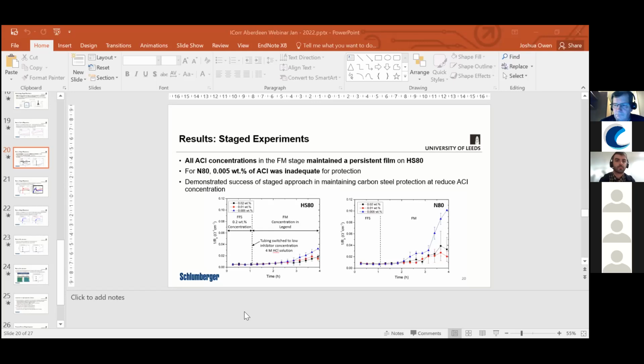It's very high. It's from 700 to 1,000 millimeters per year. It's not surprised us. So it also depends on acid concentration. So yeah, it's very normal. And actually, corrosion rate nearly exponentially increases with temperature, and also nearly exponentially increases with acid concentration, despite some rule.